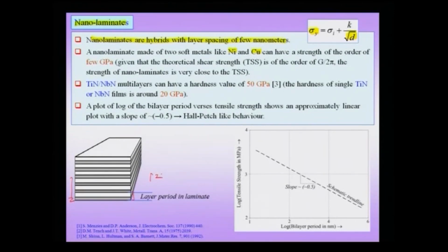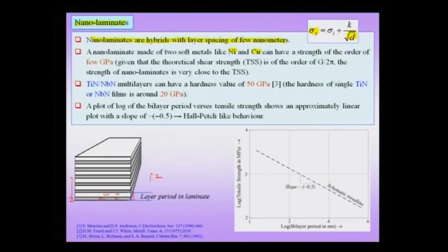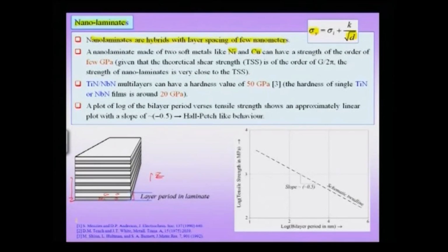Now, this implies there are two length scales in this problem. One length scale is related to the lattice parameters of each one of these crystals, and suppose I am talking about nickel and copper, then the lattice parameters of the individual components is one length scale in the problem. The second length scale is, of course, the individual layer periods, and if I take them to be equal, then I need to talk about the periodicity along the z direction, which I just described, which is an additional lattice parameter in the structure. Now, such a structure can be called a super lattice in the z direction, and the reason that you tend to form such kinds of composites is because you get additional benefits which are not found in either one of those individual components.